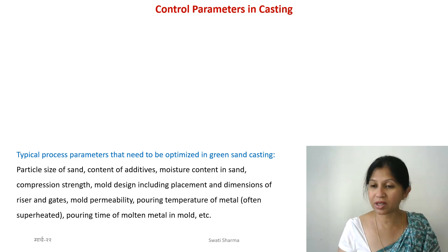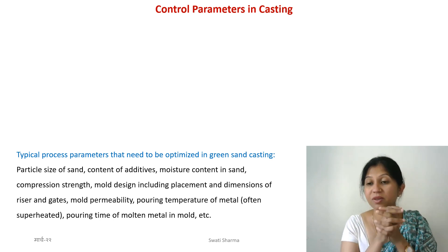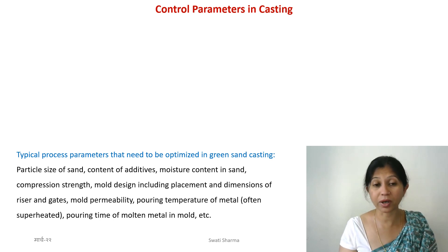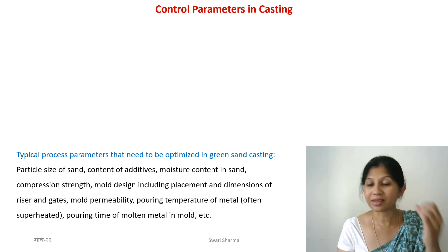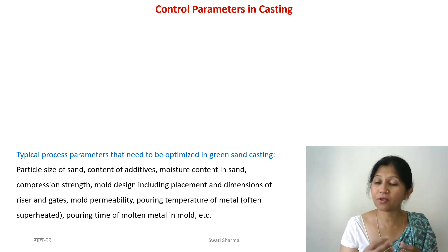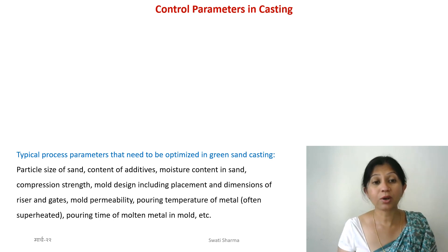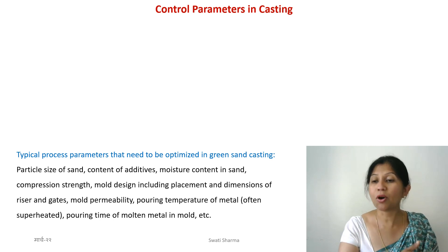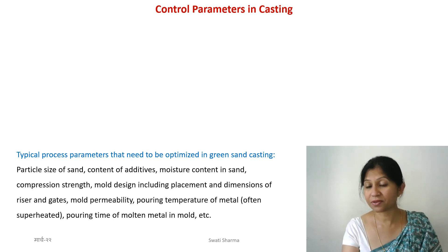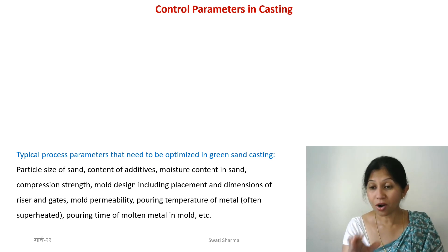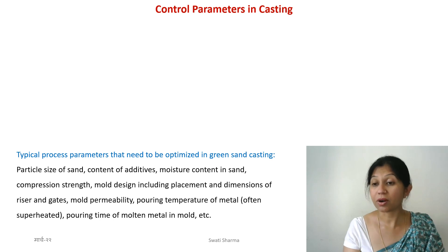The particle size of sand is important. Sand can get displaced and there can be porosity, but many of these problems can be avoided with a uniform particle size within the right range — very big or extremely small grains may not work. You also need to control the content of additives: binders and clay mixed into the sand. The clay fraction differs for ferrous and non-ferrous materials, and you need to optimize these according to your specific part.